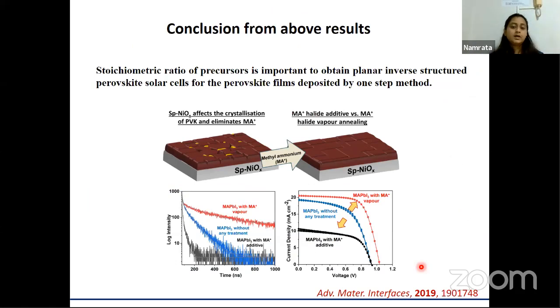So from the above study, we concluded that the stoichiometric ratio of precursors is important to obtain planar inverted structure perovskite solar cells for the perovskite films deposited by the one-step method. And if you want to read more about it, this has been published in Advanced Materials Interfaces, and you can look into the details about this study.